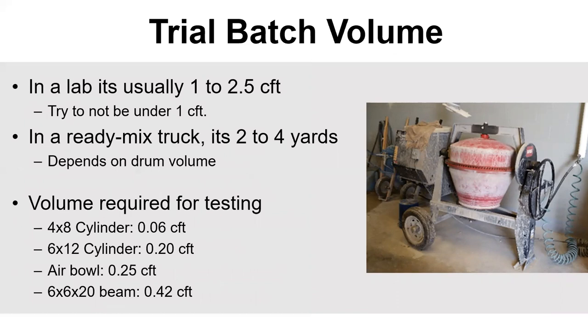Some problems I've seen with trial batching: people don't always use a large enough volume for their mixers. For example, a three-and-a-half cubic foot mixer — you really can't use anything less than about one cubic foot. When you get under that one cubic foot mark with coarse aggregate and everything else, it really becomes 'lab creek' and may not look like what you're going to see in the field.